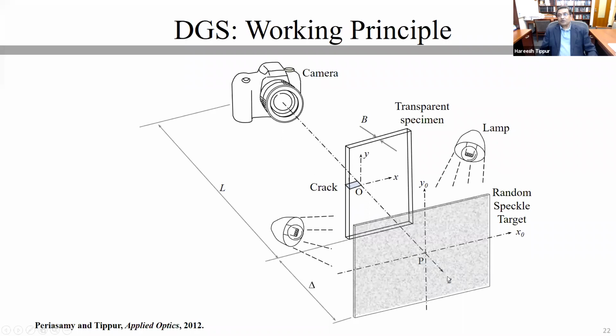Therefore, here, when we have no load on the specimen, when you take a picture of the speckle pattern, a point P gets imaged through a point O on the specimen plane by a pixel of the camera. So when I load the specimen, there is going to be a state of stress everywhere in the specimen. And you have thickness changes as well as refractive index changes that occur. And as a result, if I were to take a picture of the speckle pattern, I'll be photographing a neighboring point of P, not the same point. Now it is identified as Q by the same point on the specimen surface by the same pixel of the camera. So now I have two images, one in the deformed state and the other in the undeformed state. When I correlate the two, I get these pseudo speckle shifts.